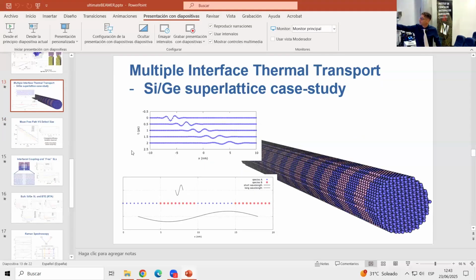That is the point. It doesn't matter what the superlattice period is, as long as you have, of course, phonons which are, you need a superlattice. So you need enough atoms inside the primitive cell to allow a localized perturbation to exist and propagate within it. If you don't, if you just have one species, one red dot and one blue dot, that is a molecule. So you don't have coherent transport in gallium arsenide, for example. You need a superlattice. So you need a primitive cell which is large enough to allow localized phonon modes to exist within the cell and to travel within the cell and experience a sequence of interfaces. But as soon as you have it, you will observe a minima.